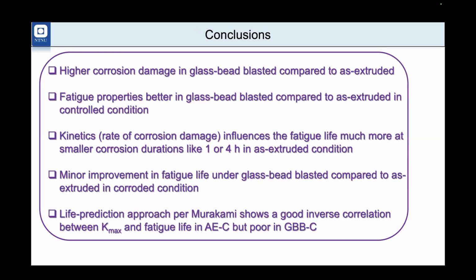The corrosion damage in glass bead blasted is higher compared to as-extruded, and the fatigue properties are obviously better in glass bead blasted compared to as-extruded because of the reasons I mentioned above: compressive residual stress and work hardening. But if you compare in the corrosion condition, the improvement in fatigue life in glass bead blasted compared to the corroded condition is less. That's because there's significant curtailing of the crack initiation phase as a result of the prior corrosion.